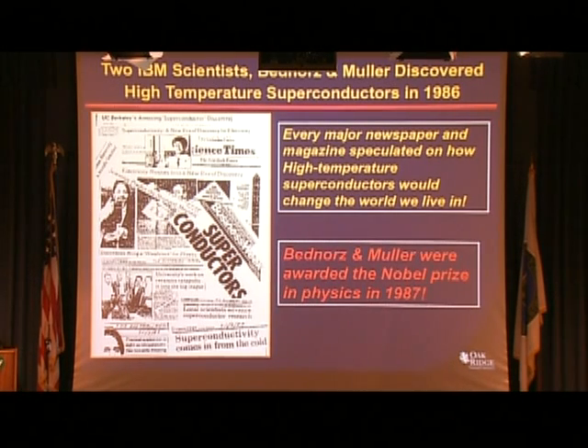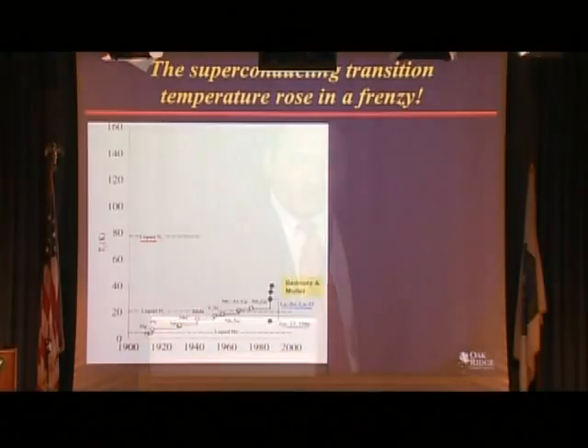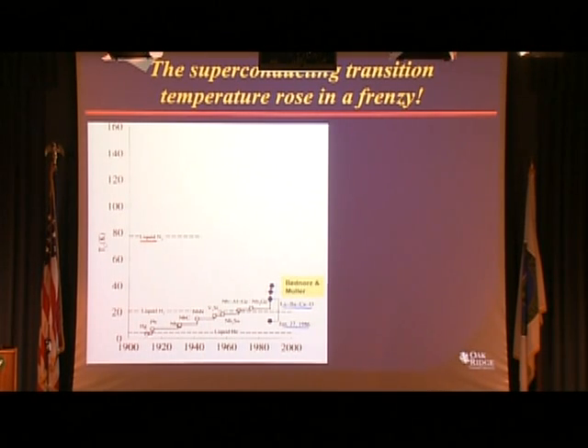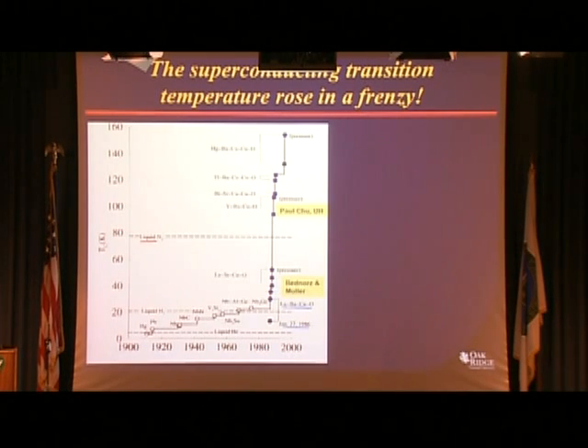As Secretary Chu pointed out, they were awarded a Nobel Prize a year later in 1987, and typically Nobel Prizes are awarded for work that's been done several years back, or many years back. So part of the reason why perhaps this occurred was the tremendous potential applications that these materials had. The superconducting transition temperature, or the temperature at which these materials go superconducting, had not changed much if you were to plot the transition temperature versus year until Bednorz and Mueller discovered these cuprate-based superconductors with a transition temperature of 40 Kelvin. That was very exciting. Not only that, Paul Chu and his group quickly discovered what's called the yttrium barium copper oxide superconductor, which had a transition temperature close to 90 Kelvin. And the transition temperature kept going up, the mercury-based superconductor being close to 140 Kelvin, and with pressures close to 160 Kelvin. Those were exciting days.